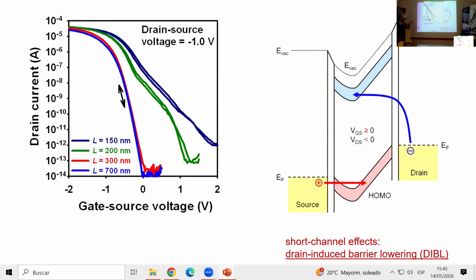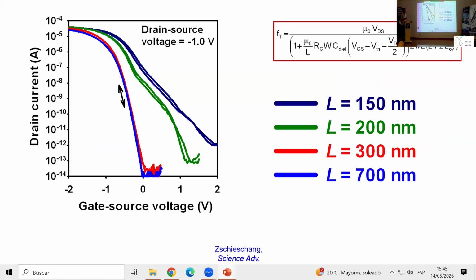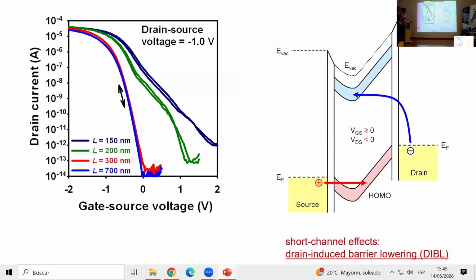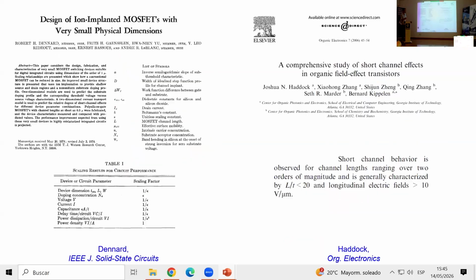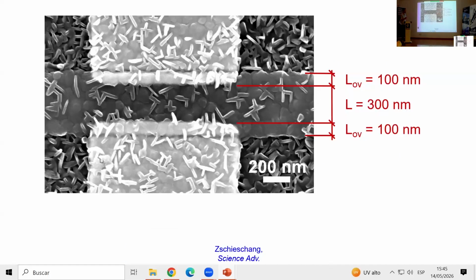And so even though the equation for the transit frequency predicts that we should make the channel length as small as possible, there's a limit in terms of how small we should be making the channel length if we want to be able to maintain the minimum possible off-state drain current here, and that limit is currently on the order of 300 nanometers. Okay. Now this is not new. This was developed for silicon MOSFETs about 60 years ago, and it was reiterated for organic transistors about 20 years ago. Okay, so this is not news.